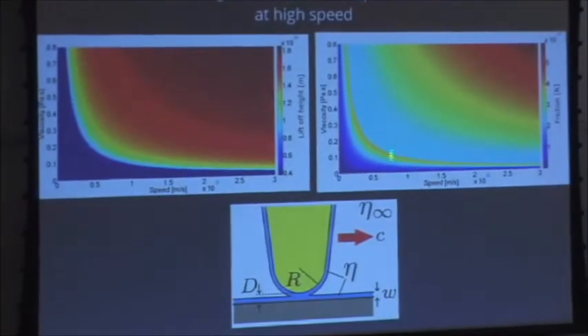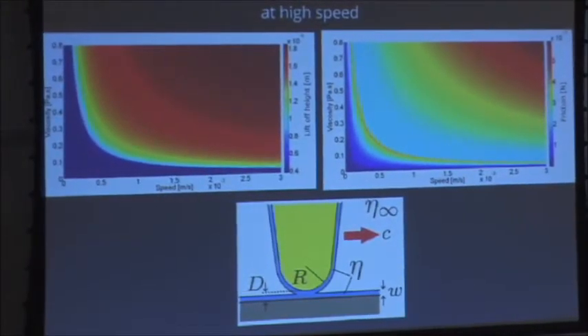If we increase the speed, supposing our viscosity is 0.3, at some velocity, about 0.5 millimeters per second, we'll undergo a transition where the viscosity suddenly goes down. So we come here and it suddenly drops. Over here you've got the friction. Again, if you go to a reasonably high speed, about 1 millimeter per second, there's a transition as you cross that. You can then vary other parameters, the tip radius, the load you apply. What you're seeing is that at about a millimeter per second there's a transition, and what's happening is the tip is lifting off the surface.